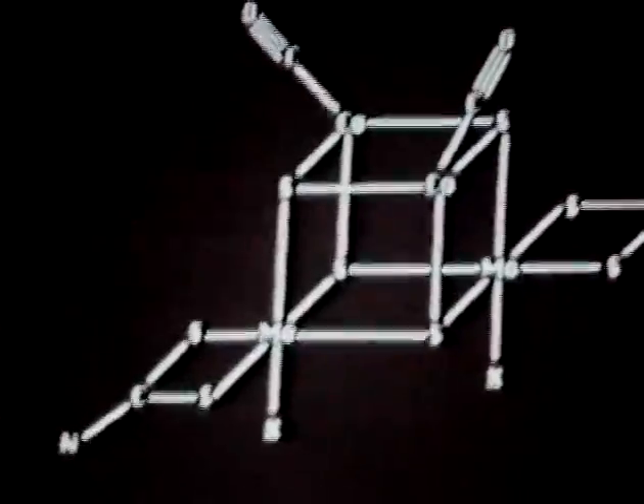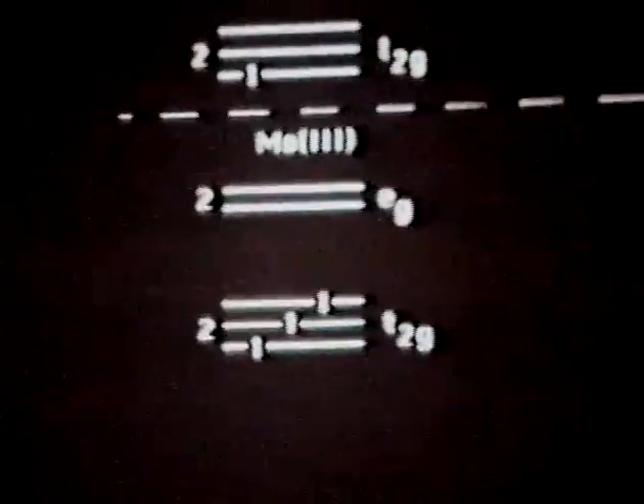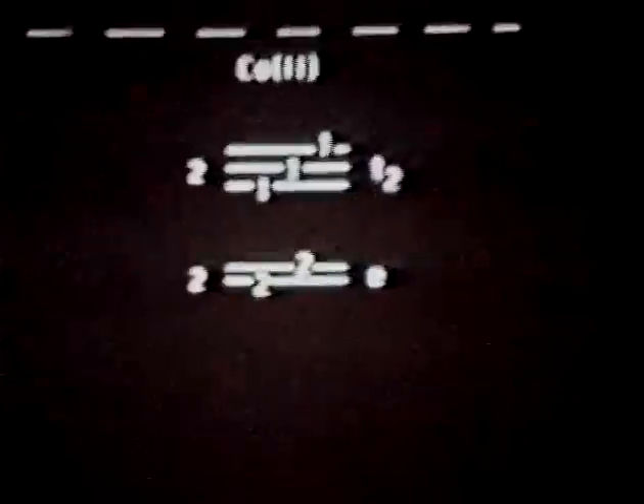This is basically the same molecule again, and I just wanted to show you that the electronic formulation shown on the bottom here, cobalt-2 and molybdenum-3, is exactly the one that I was talking about before in theory. However, the inorganic chemist will say that this formulation is, in reality, equally as valid as this one. And in this case, it has cobalt-0 on the molybdenum-5 molecule.